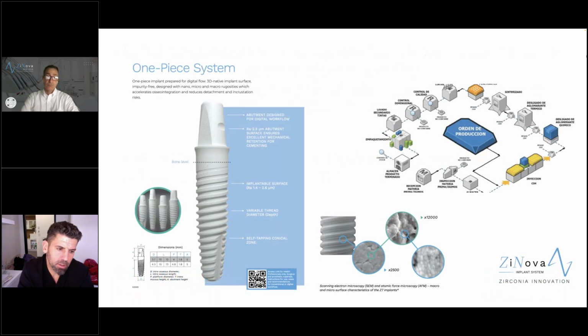This is the ZiNova one-piece system. Like other one-piece systems available, you have a bone level, and then you have a tissue level portion of the implant. The implantable surface, the bone level surface, has a roughness of about 1.4 to 2.6 microns. So this is a moderately rough implant surface.